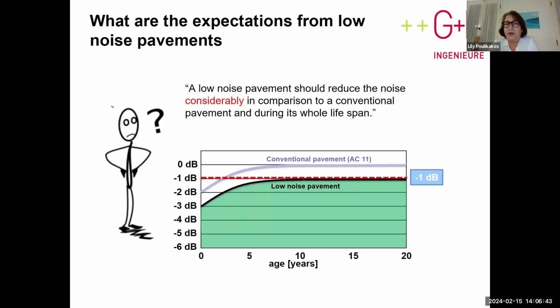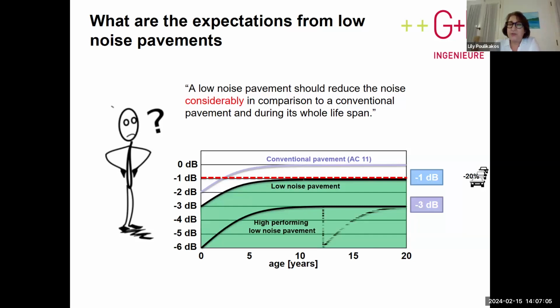If we compare the low noise pavement to a conventional pavement, in this case it's AC11, if we reduce the noise by 1 decibel throughout the lifetime, that is equivalent to reducing the traffic by 20%. If we reduce the noise by 3 decibels, that is equivalent to reducing it by 50%. And in this case, we probably would have to replace the pavement after about 12 years. This is what is done normally in Switzerland. And if we can reduce it by 6 decibels, then we can reduce the traffic by 75%.